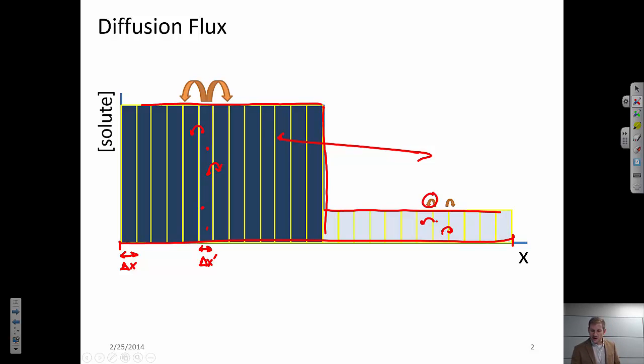But this flux, this transport of solute atoms from this bin to the left or this bin to the right, is going to be smaller than it is over in this case. And that's simply because we have less atoms to begin with. The overall concentration of solute is much less. And so if I give each individual atom some constant probability of staying in the bin, bouncing out to the right, or bouncing out to the left, then that's going to result in smaller fluxes in this case and larger fluxes in that case.